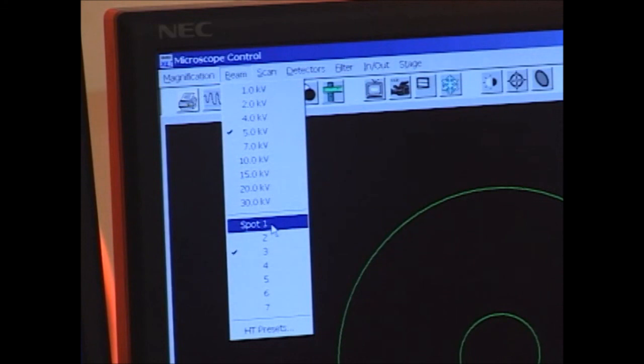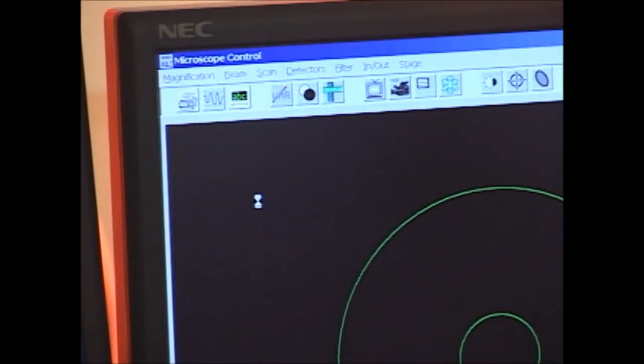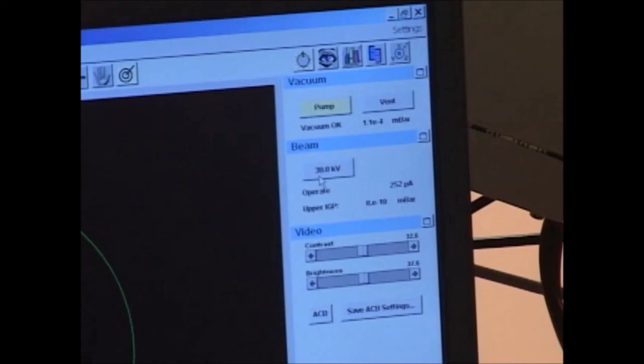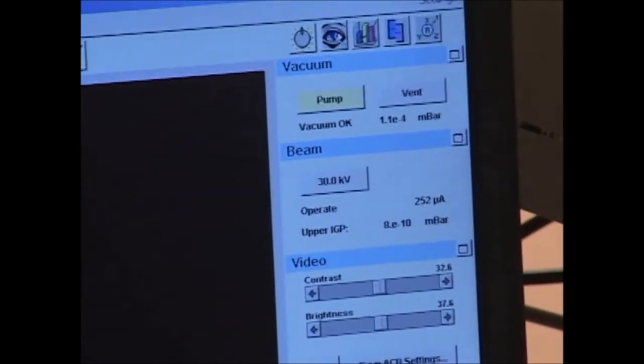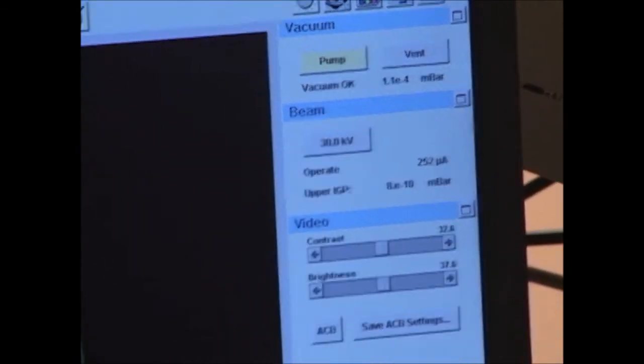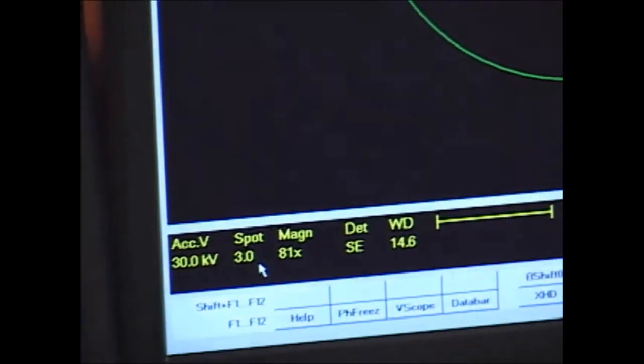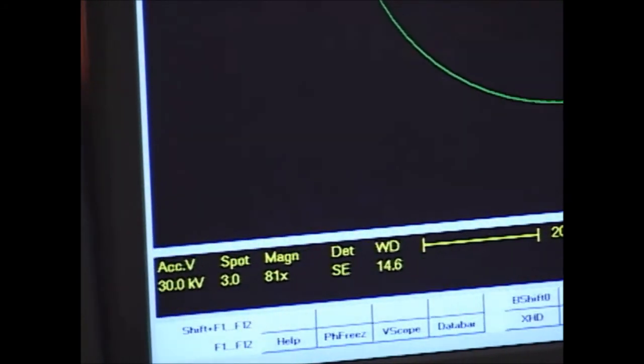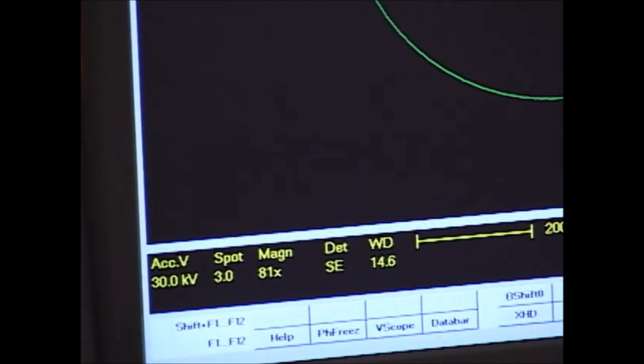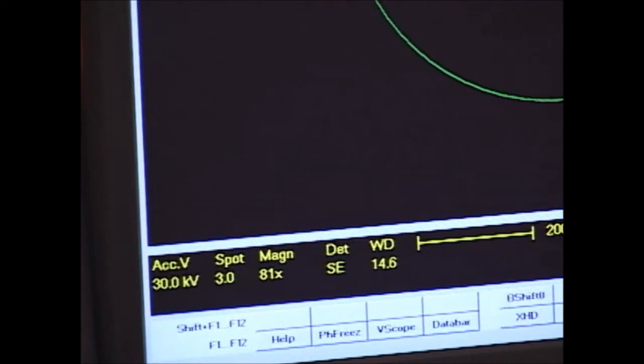So I'm just going to set this one to 30 kV because our standard sample is a really good conductor and it can tolerate this without any difficulty. And then you see that under the beam menu, the button has changed to 30 kV, so it reflects the actual accelerating voltage that you're going to use. Also in the data bar down here, you can see accelerating voltage has changed to 30 kV, spot size 3.